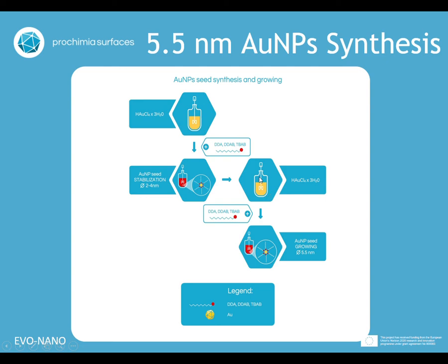of the next portion of tetrachloroauric acid in the presence of the stabilizing agents. And then you can see that in this way we obtained 5.5 nanometers. The synthesis is performed stepwise because it provides much more monodispersed gold nanoparticles instead of the preparation in one step.